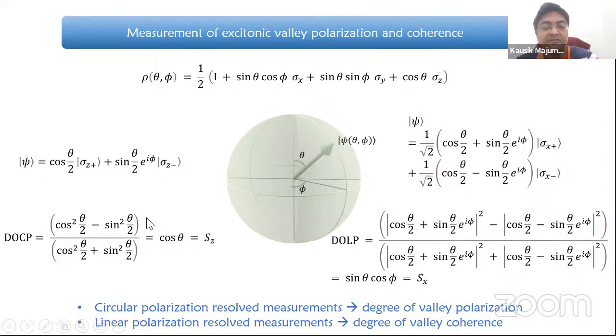Degree of circular polarization tells you, suppose you are exciting the system with sigma plus circularly polarized light, and you are measuring in co and cross polarization, meaning your analyzer is either sigma plus or sigma minus, and you find I1 minus I2 over I1 plus I2. Mathematically you can show that it's really the coefficient of sigma z. So the DOCP directly corresponds to the valley polarization of the system.